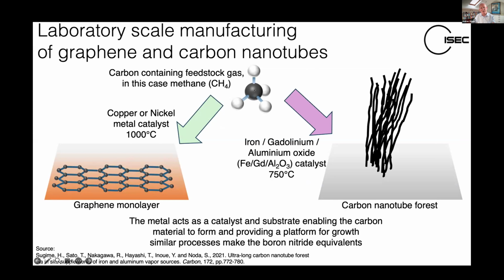And here you can see that we start off with something called methane gas, or methane as you'd refer to it in America. This is the gas that comes out of your pipes at home or is dug out of the ground, and it contains carbon with hydrogens on it. And you bring it close to the surface of a metal catalyst around about 1,000 degrees, and that allows the carbon to come off, the hydrogen to come off.